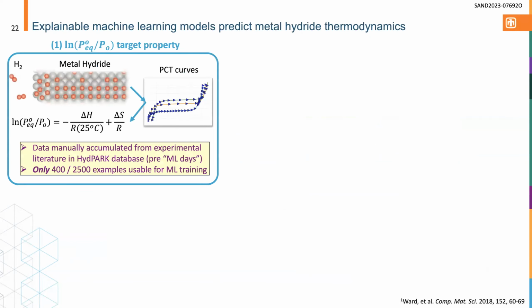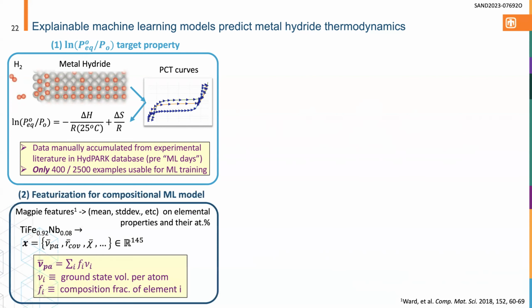So quickly again, I mentioned what a metal hydride was. I'll just quickly recap. You have a metal and you expose it to hydrogen gas. The hydrogen dissociates at the surface and then migrates into the bulk. A useful hydride material is one that undergoes a phase transition, basically an alpha to beta phase transition, which results in this plateau you see on the right in this pressure-composition-temperature space. So basically, within a very small pressure window, you can release a lot of hydrogen.